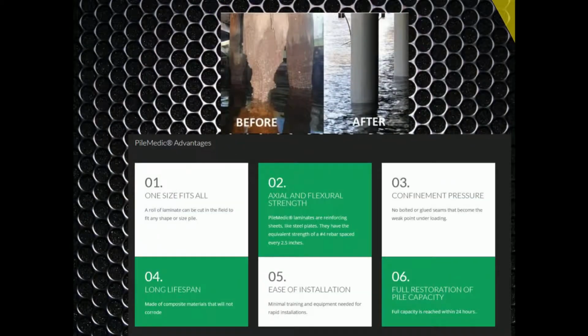The main competitive advantage that PileMedic has compared to all the other jacketing systems is primarily its ability to introduce a tremendous amount of capacity without the use of bulky forms or labor-intensive rebar cages. In addition to that, the fact that one size fits all, you're pulling this off of one roll of material to make any size pile jacket. It's increasing axial and flexural strength without the use of rebar, in some cases with additional rebar for bending. It's providing a tremendous confinement pressure due to the lack of seams, which is the main reason for its ability to increase capacity.